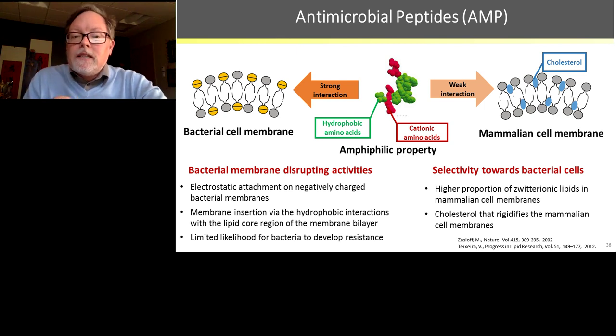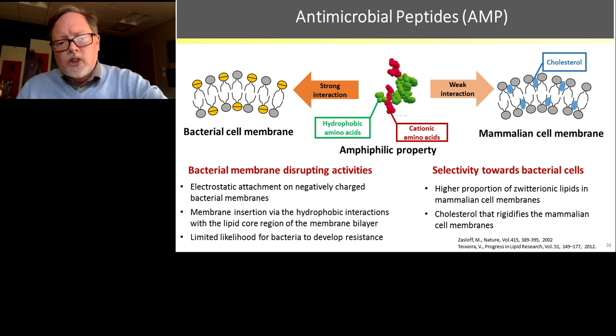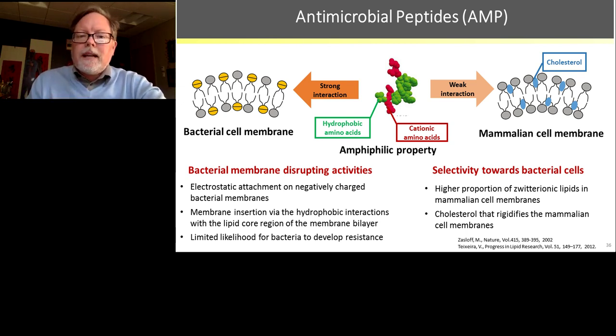What is nice about these self-assembled antimicrobial peptides is they have a very strong interaction with a bacteria cell membrane, as you can see on the left, but they have a weak interaction with mammalian cell membranes. And really the reason for that is mammalian cells, which we don't want to kill, have things like cholesterol, they have other proteins that are present in the cell wall, which won't be stabbed or won't be influenced by these self-assembled chemistries. So they're really selective towards killing bacteria, which is very, very important.